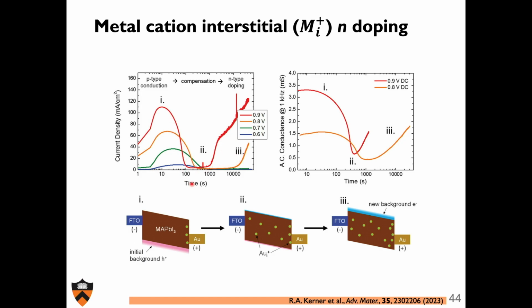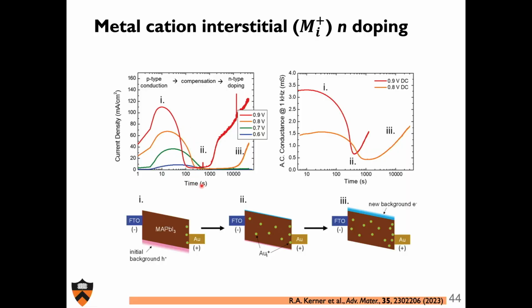And I go through this plateau. And we think this is where you're basically compensating that semiconductor. So I had an initial hole population. Every time I inject a gold interstitial, I also inject an electron, and that is compensating the system. It's becoming basically insulating. You can see my current falls off, and then eventually my current comes back up when I achieve n-type doping. And that was consistent with the impedance analysis that we did as well. So this is what we think is happening. You have initially p-type conduction, then the system becomes compensated, and then eventually you get an n-type medium.